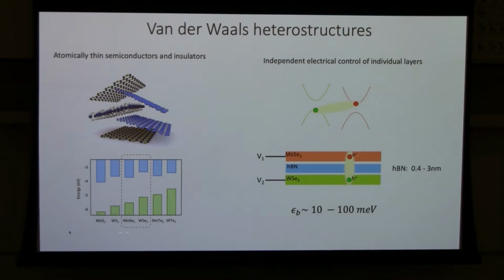So these are six examples. They have different band gaps and different band alignments. If we just choose two of them, say MoSe2 and WSe2, they have so-called type 2 band alignment. The conduction band minimum is in MoSe2 and the valence band maximum is in WSe2. So if you simply stack them together, the conduction and valence bands don't overlap, so you don't naturally have electron-hole bilayers.